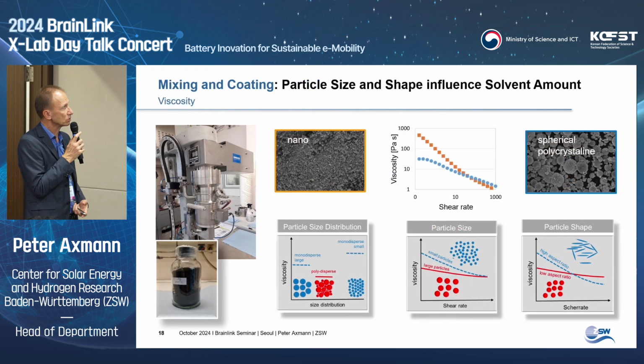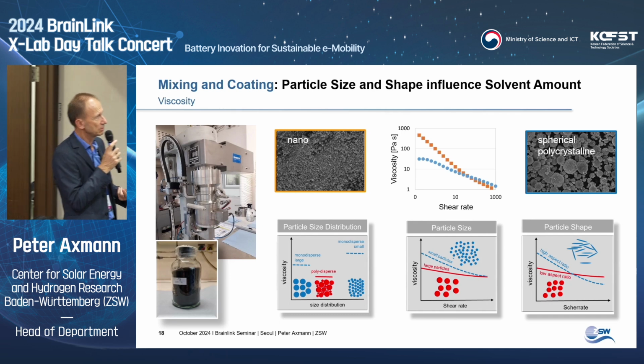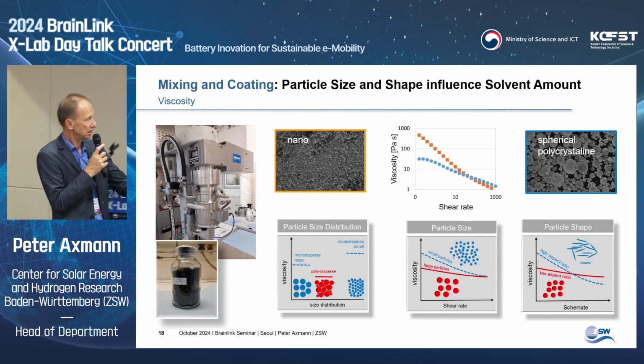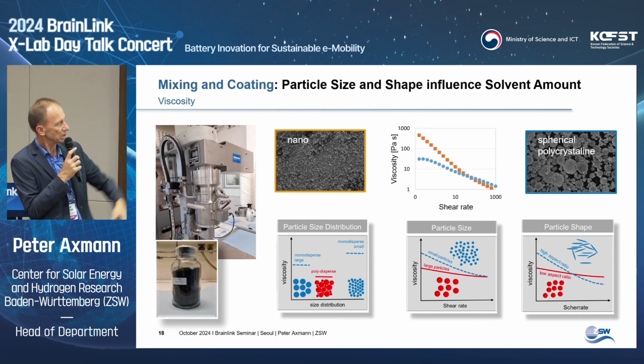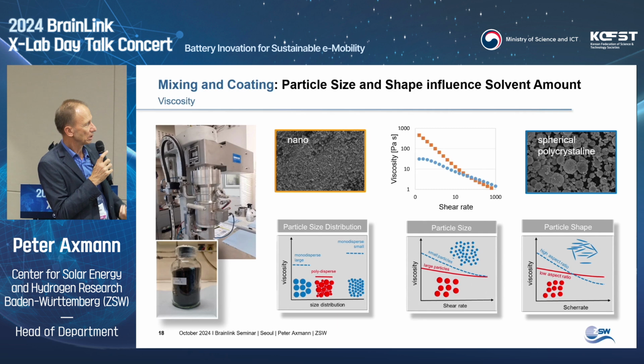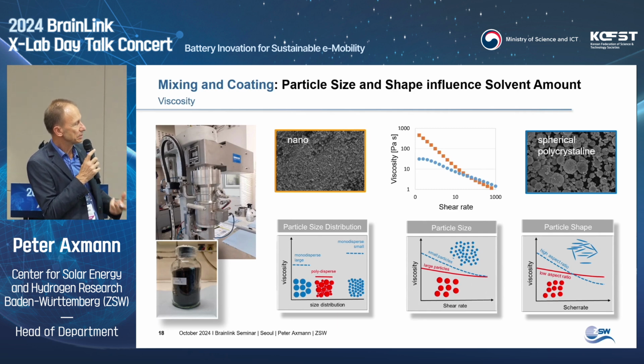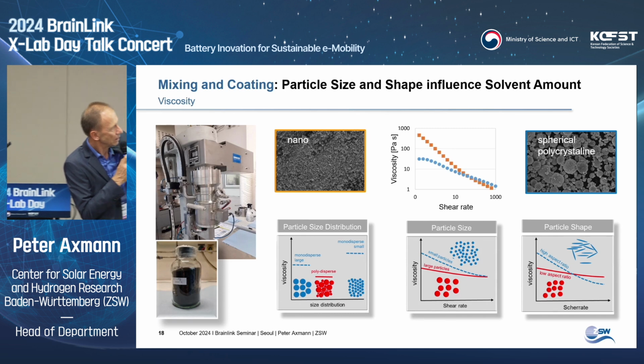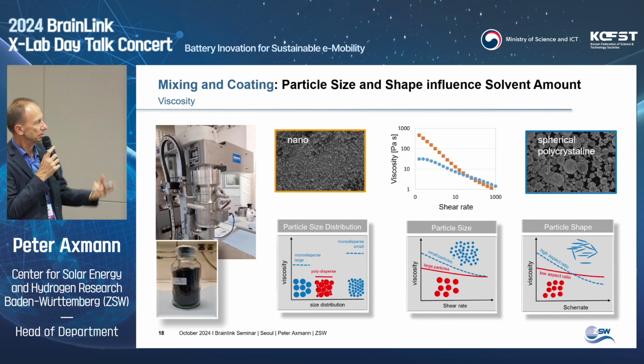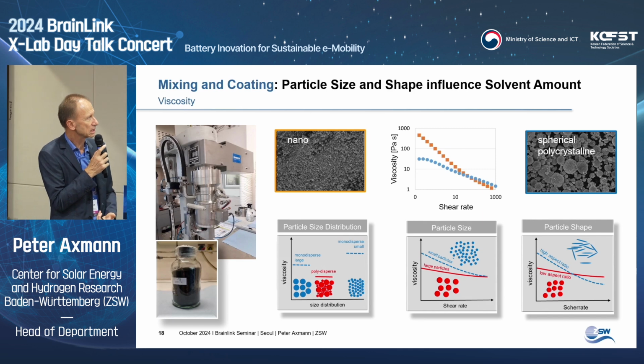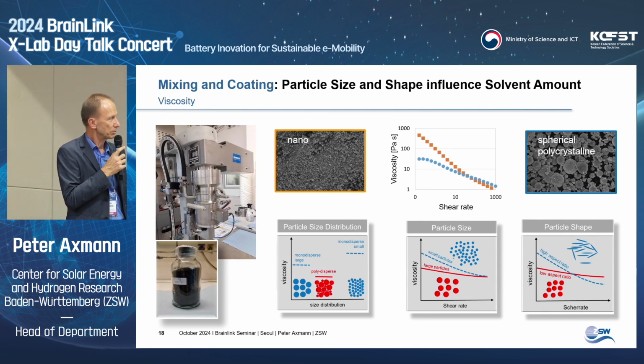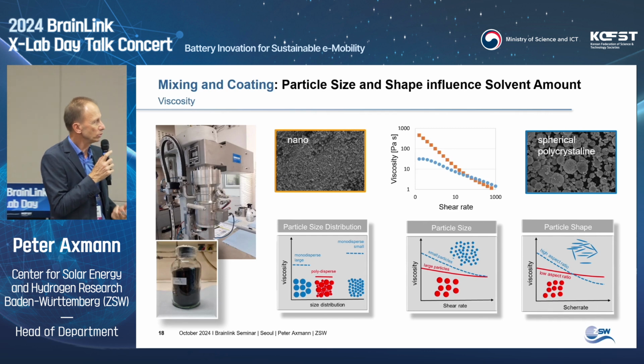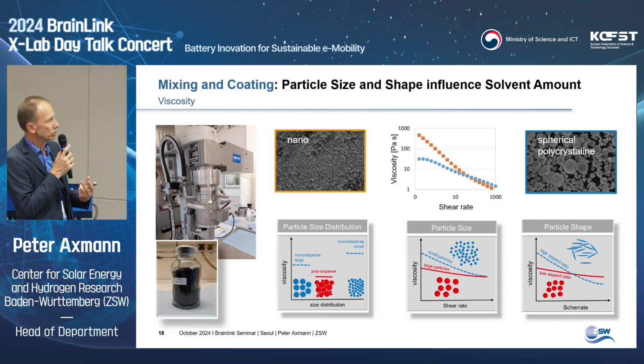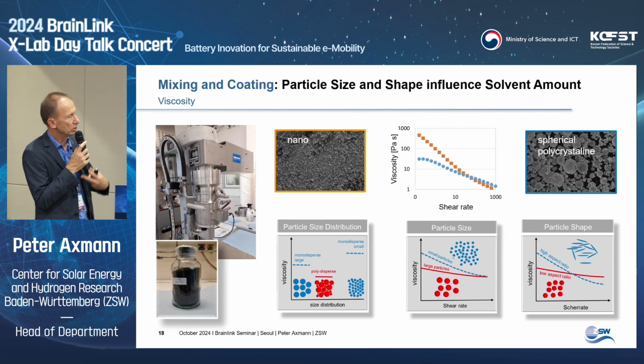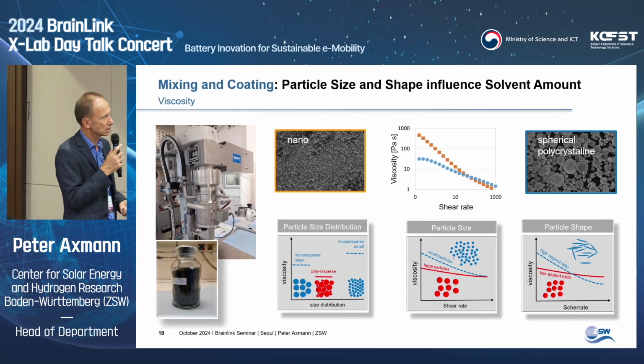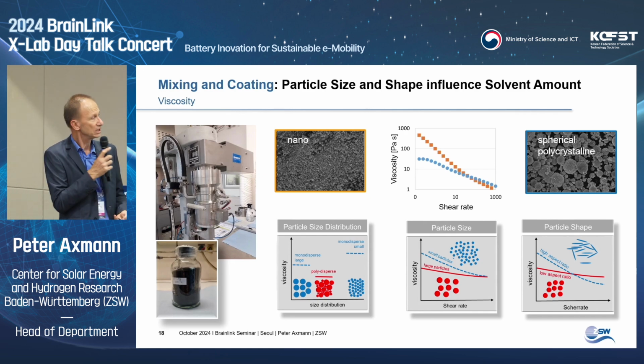Starting with mixing and coating, particle size and shape influence the solvent amount you need in mixing. You can see it here for a nanomaterial and a spherical polycrystalline material. Both are lithium iron phosphates. Both have been mixed with the same recipe, same solvent amount, and we see the viscosity of the nanomaterial, the orange line, is much higher compared to the spherical polycrystalline material. And this means to reach optimum coating viscosity, you need to dilute it much more than the other material. Use more solvent, you need more drying energy, you need to coat thicker layers, so there is a large influence on the coating behavior and the effectivity of the coating.